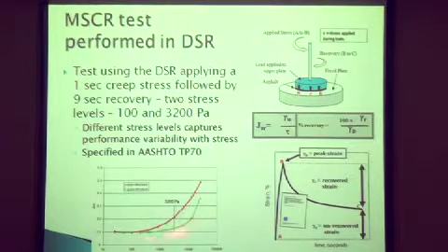This green binder, red binder. What we have here are tests conducted at different levels of stress. Now, in the standard MSCR test, we use stress levels of 100 and 3,200 pascals. 100 is here. 100 pascals is a very low level of stress. It's basically in the linear region.